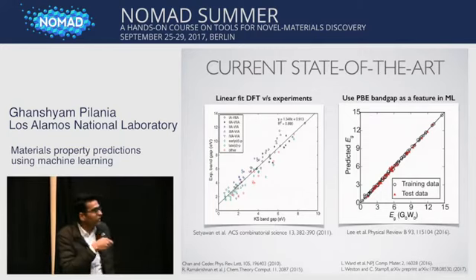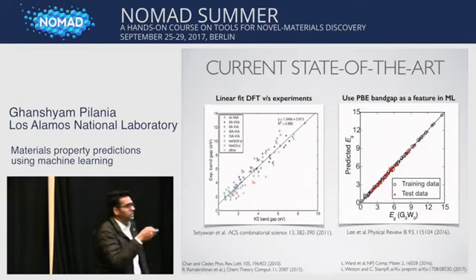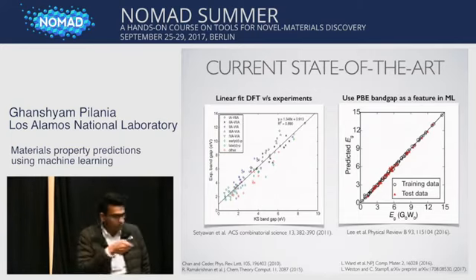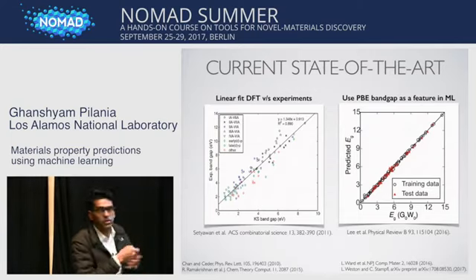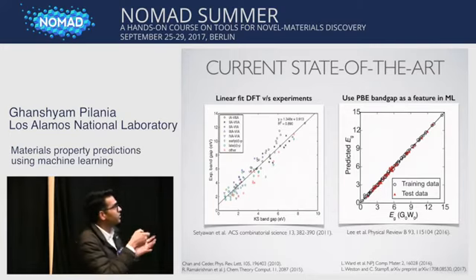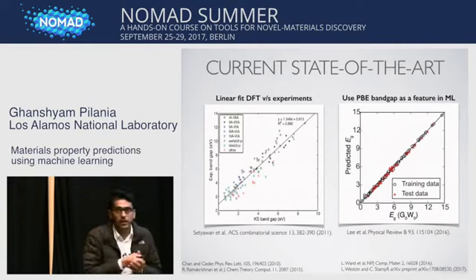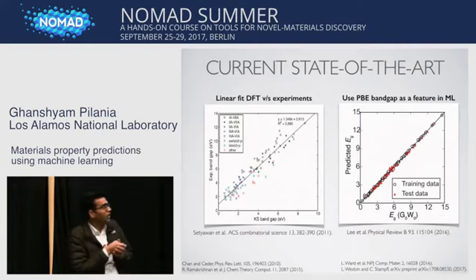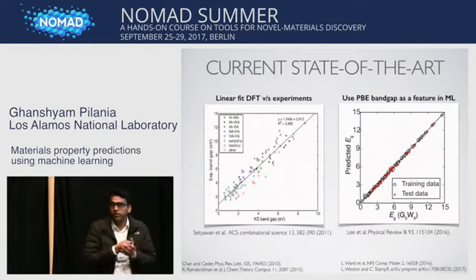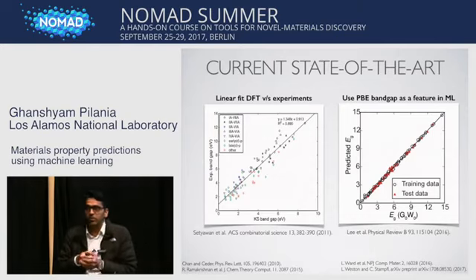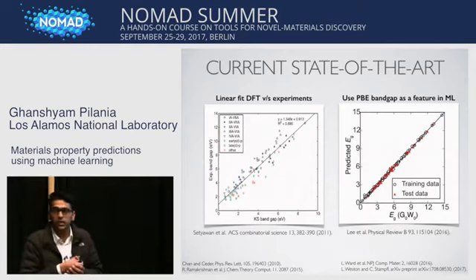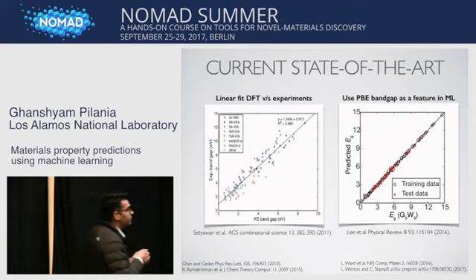So the co-Kriging model that was presented combines the best of these both worlds. So you can make much more efficient predictions. At the same time, you don't really need PBE band gaps as a feature. If you have low fidelity data, you can always include it, but if it's not there, then still predictions can be made. So it's not a limiting restriction.